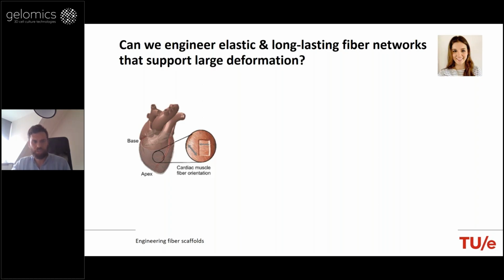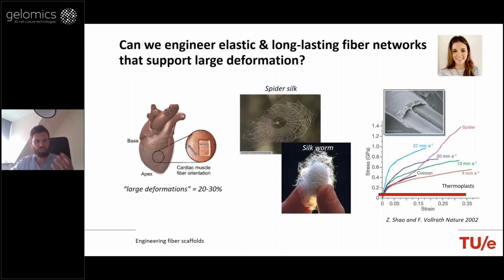of silk. So one of the challenges is to come up with a process that when we extract it with the existing processes, like taking in this case the silkworms from a cocoon, digest the cocoons, isolate the extract the silk fibroin, and then we get rid of the sericin, was to how do we restore the beta sheets and organization of the silk molecules in order to achieve the same elastic behavior and strength that is characteristic of silk.